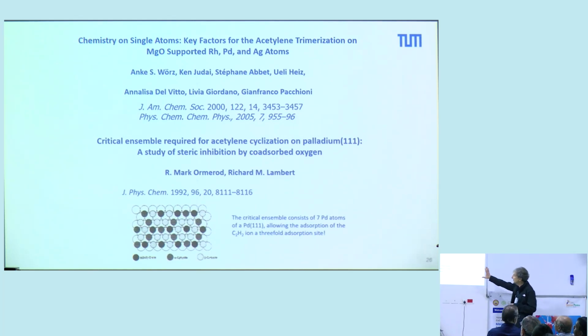And so the motivation for this work was that it has been shown on single crystals that you can have a cyclotrimerization. You have C2H2, and it can produce benzene. And in the surface science studies, it has been speculated that you need an ensemble of 7 palladium atoms in order that this reaction takes place. So this was our motivation to study the size dependency of this cyclotrimerization, expecting that we need a critical size. But we were